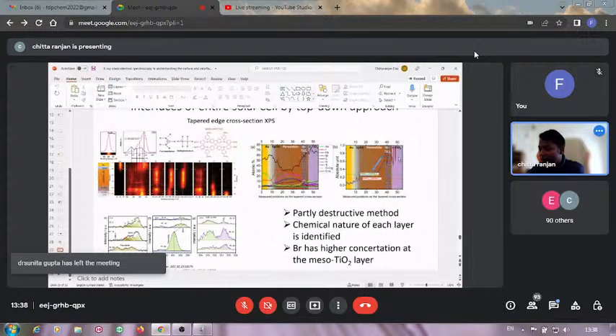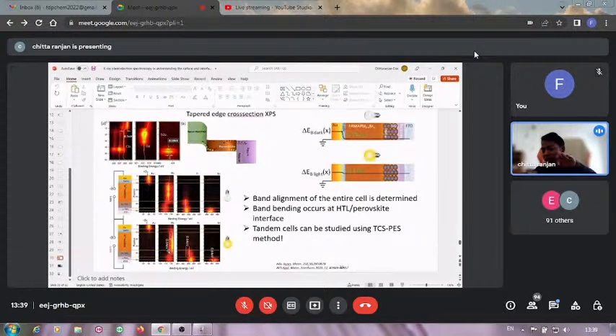Again, the same example, like here we measure in the dark. If you can see, we measure in the dark, it's over here. And when you put light, it shifts to higher binding energy. And this is approximately 0.6 electron volt, and this 0.6 electron volt is called open circuit potential. That means the difference between one layer of perovskite or semiconductor and another layer of semiconductor. In this case, it's the perovskite and the hole transporting layer. And here you can see this is the open circuit potential. This is the voltage that you get in your solar cells. And then when you put light, it's in equilibrium with each other, and that means you are generating this amount of voltage to drag away your electrons and holes.